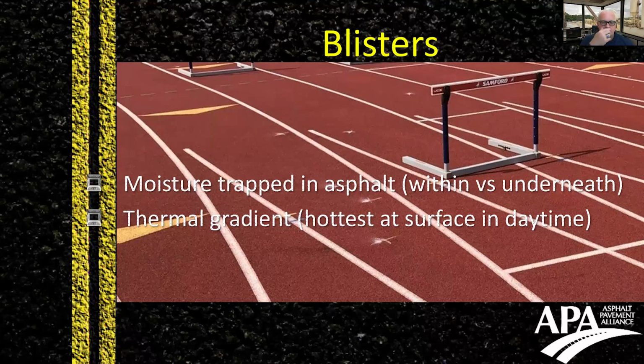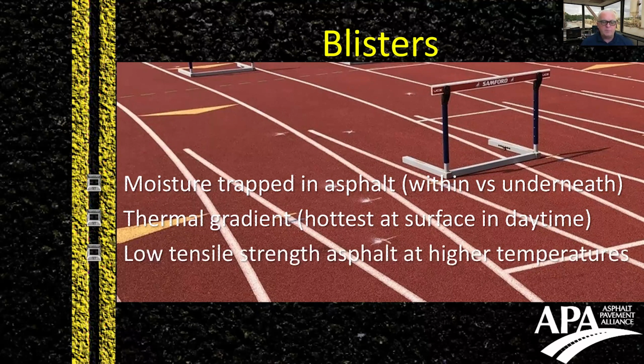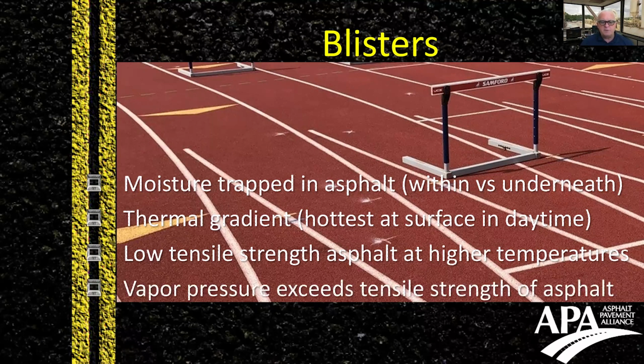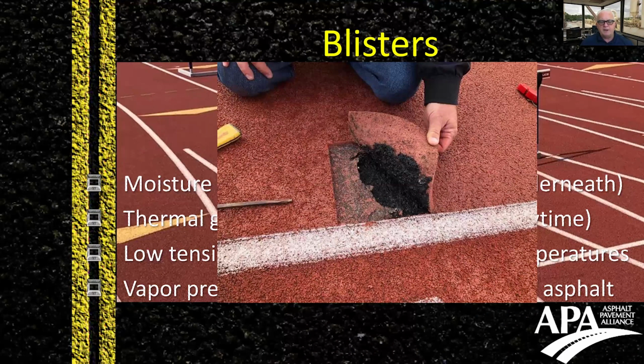And this can be an issue when you have thermal gradients. The hotter temperatures are at the surface in the daytime, so it can create pretty significant thermal gradients. At really high temperatures, asphalt is at a lower tensile strength. And then you have these blisters occur when vapor pressure exceeds the tensile strength of the asphalt. So you have water trapped in there. It gets hot. You have vapor pressure build up, and then when it exceeds the strength of the asphalt, you have these blisters occur, and then you can have delamination occur as well.